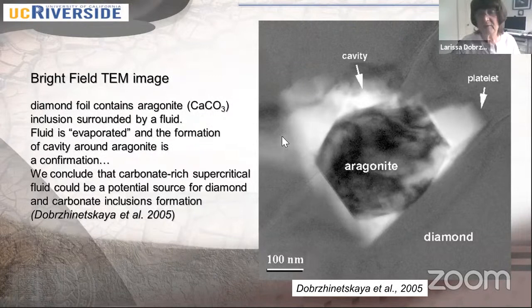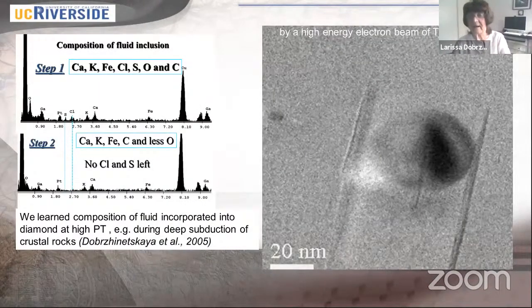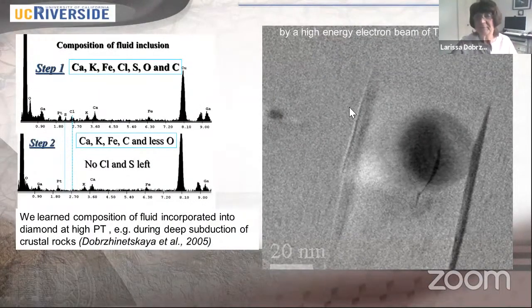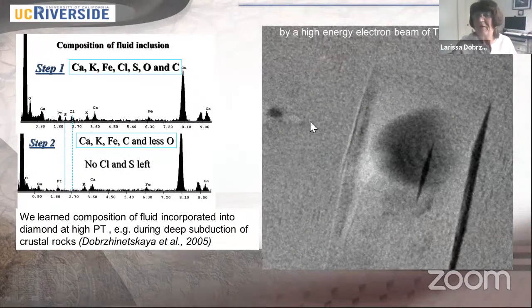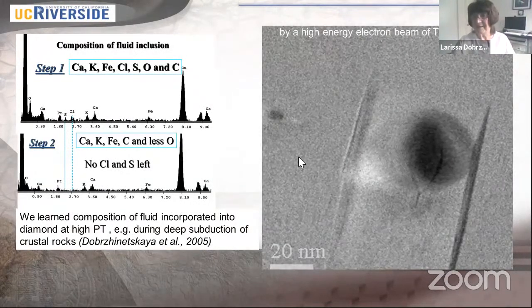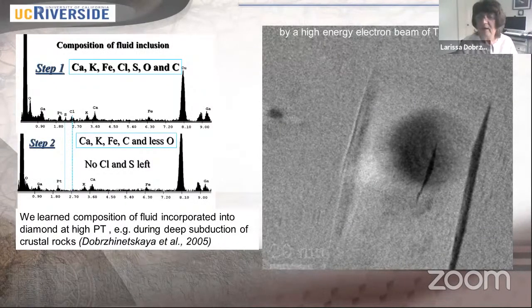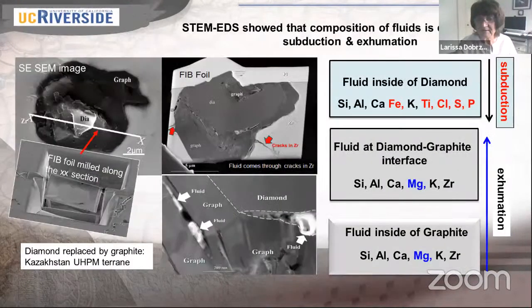Then another example of an inclusion which was surrounded by fluid is the aragonite, okay? And you see here the contrast, which is very bright. It's already a cavity. You already have a foil where the fluid was evaporated, maybe by focus ion beam when the foil was prepared. So we would like to conclude that this sample was a unique exemplar which was available for us probably by chance, because this happened not very often. Fluid can be evaporated very easily.